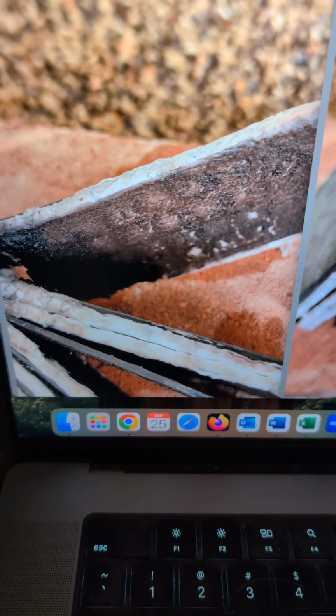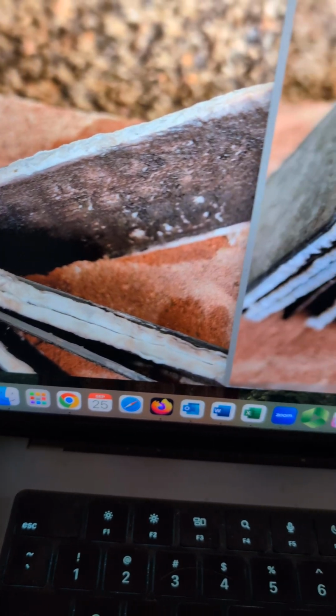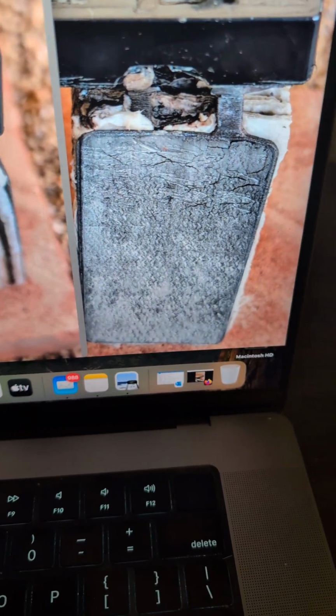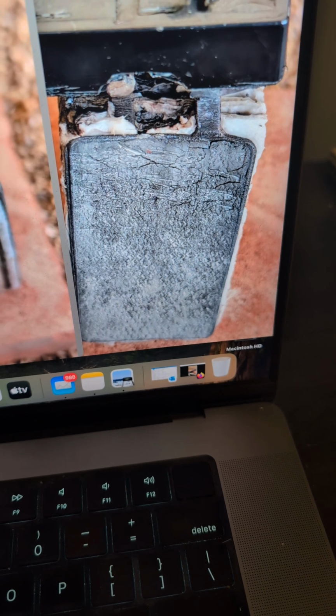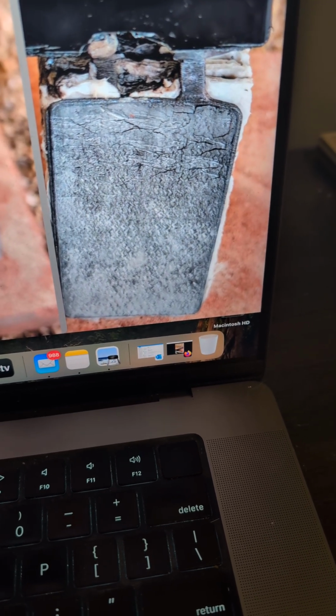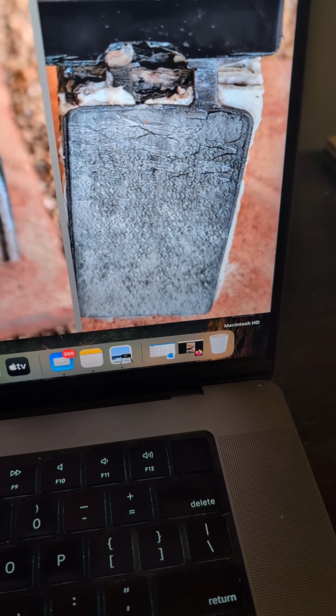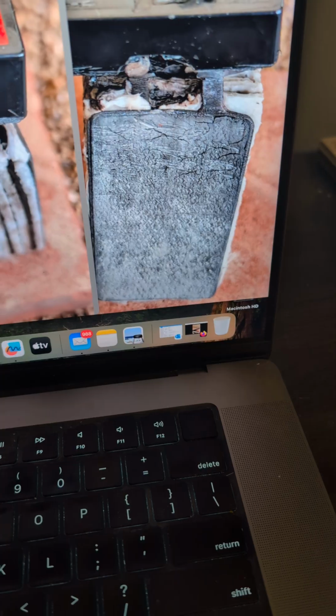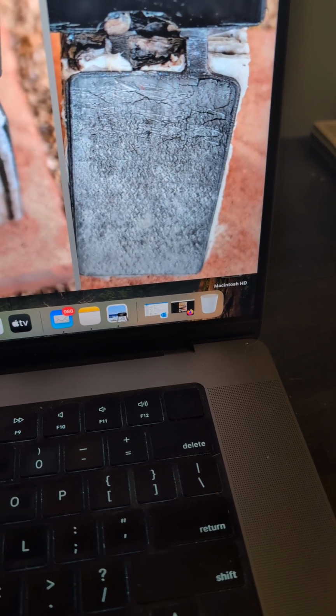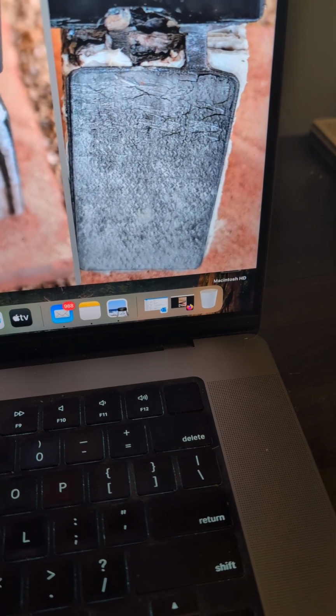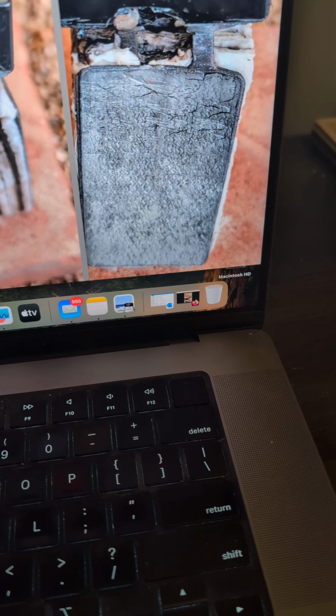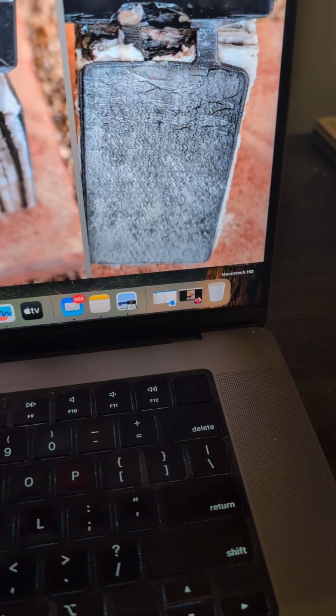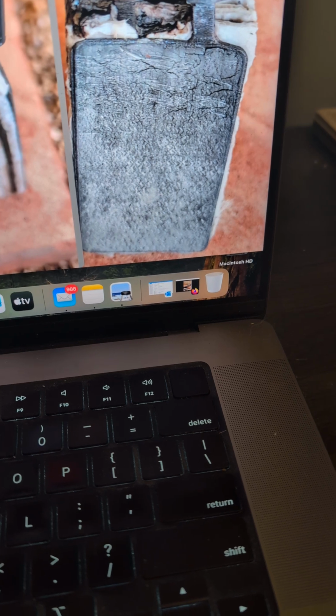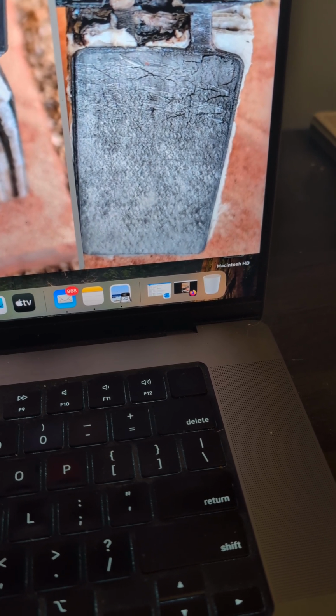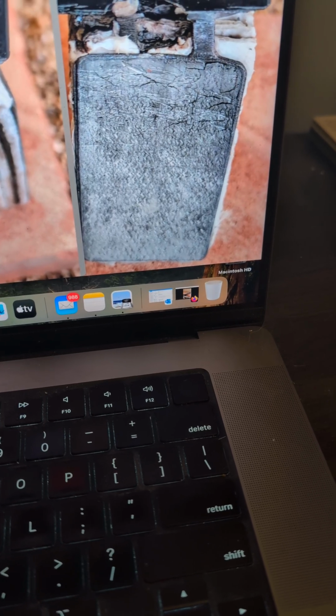And we're going to pry off the glass fiber paper separators, and we'll clip off the electrodes and do scanning electron microscopic imagery. We also have micro X-ray fluorescence, and that's valuable because we can get down to parts per million of metal contaminants. And there's a surprising number of metals that can be found in lead electrodes: antimony, tin, manganese. I did a quick artificial intelligence search on this, and there's surprisingly 2, 3, or even 4 others that can be found. So we want at the part per million level with micro X-ray fluorescence. So we want to see what's found.